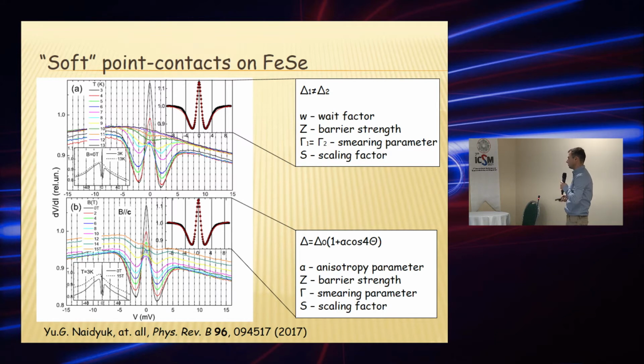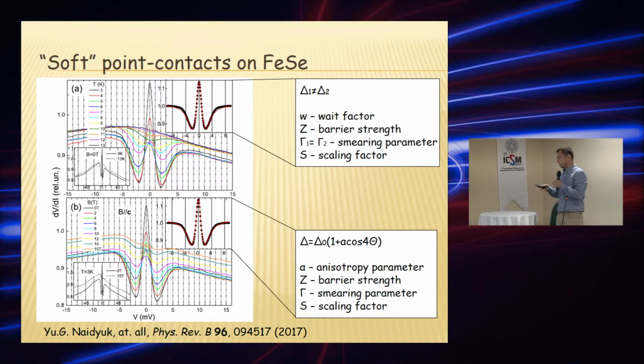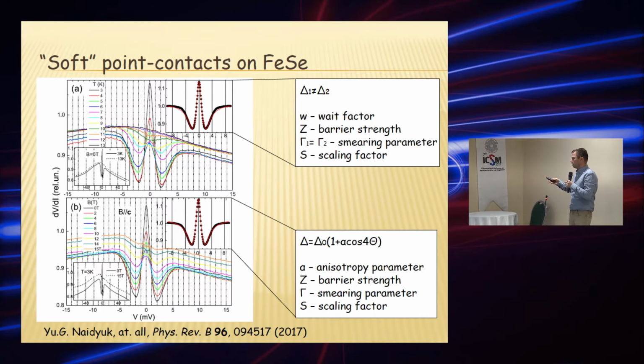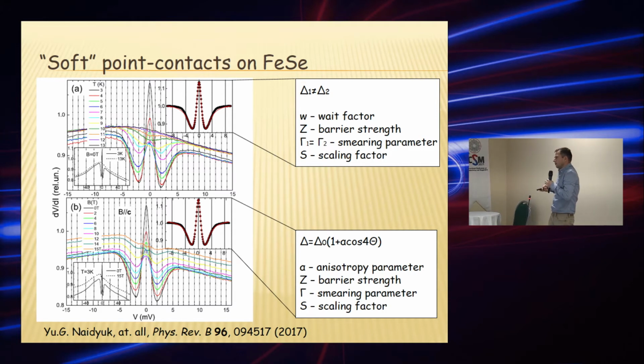The anisotropy parameter says how much our gap changes in space. If you look closer at how our fit matched the experimental data, it became obvious that the anisotropic gap works slightly better. But when we started to fit with temperature, we found that the alpha parameter starts to grow with temperature, and approaching the critical temperature it changes from 0.3 up to 1, which is physically unreasonable.